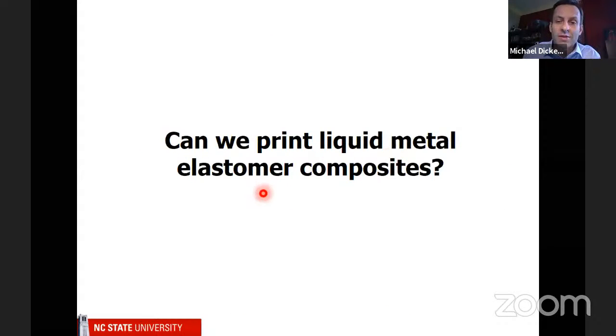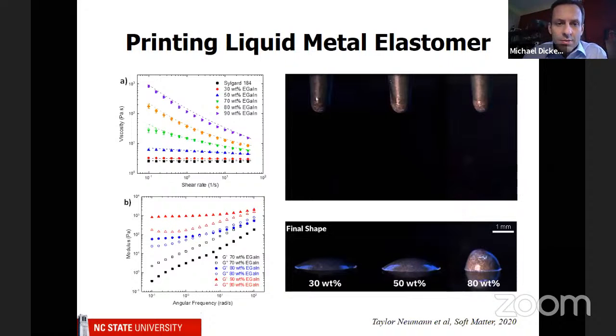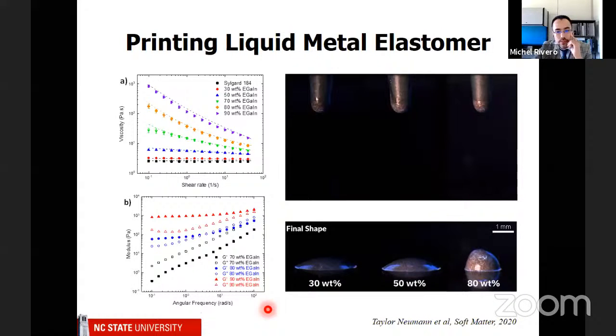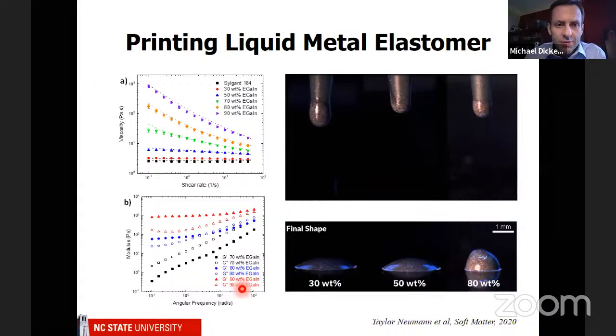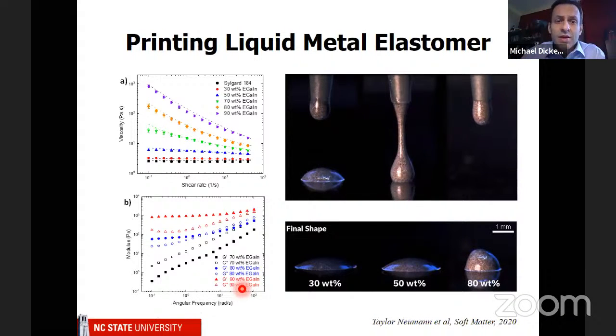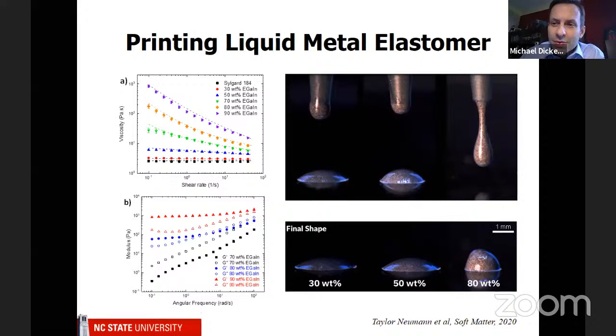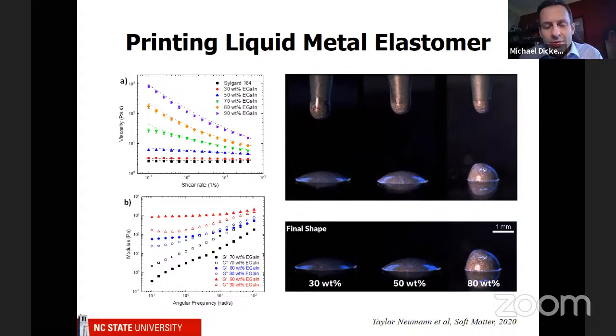So we call them liquid metal elastomer composites because the liquid metal is mixed with the silicone. So I'm going to show you what this looks like. These are 3 different nozzles that have different loadings of liquid metal. And let's see if my computer will play here. So here it comes. Okay, so the one on the left is 30 weight percent. And you can see that it's kind of runny, kind of just flows. The middle one flows a little bit. And then the one on the right, which has 80 weight percent, it's a little bit frozen here. Let's see if it's going to play. I'm sorry, the video is not playing smoothly, but you can see that it sort of holds its shape.